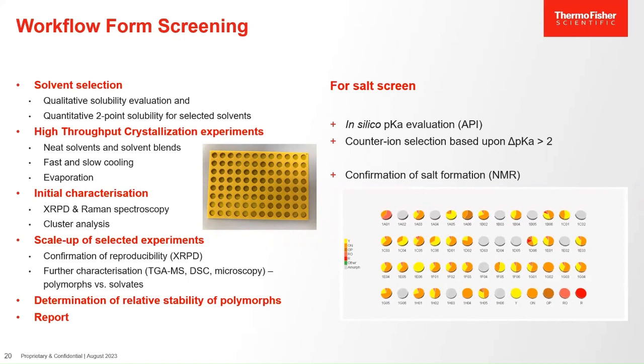Then we carry out high throughput crystallization experiments, typically in neat solvents and solvent blends, and the experiments will encompass fast and slow cooling experiments and evaporative crystallization. At the scale we work at, we can't do true anti-solvent crystallizations where we have the API in a good solvent and we add a poor solvent, but this is what our solvent blends are there for. We approximate anti-solvent crystallization by using different solvent blends of good and poor solvents.